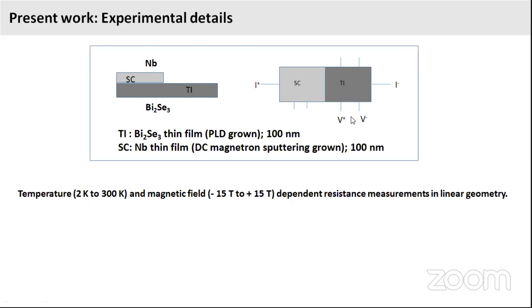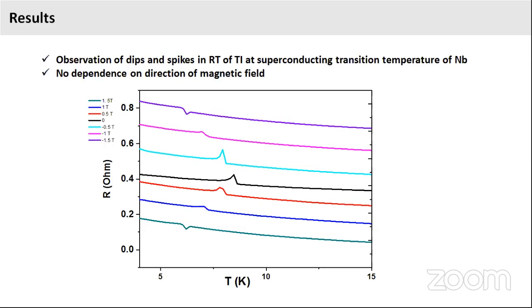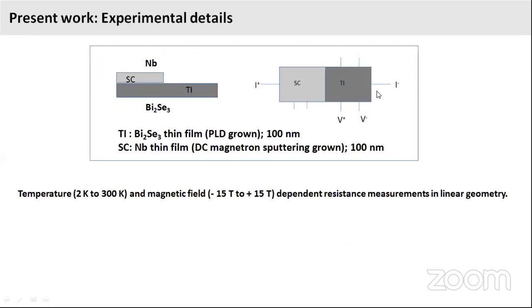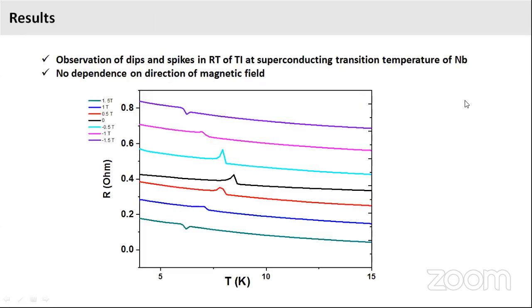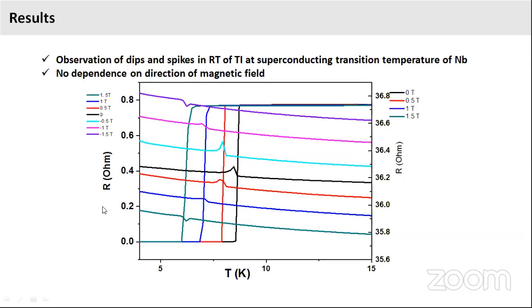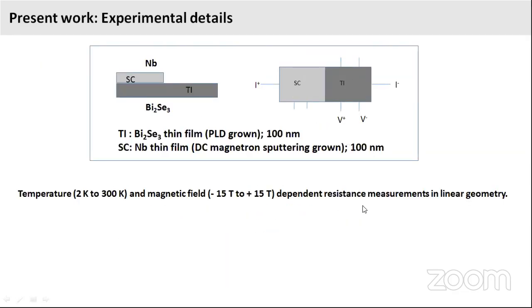Most of what I discuss today will be on what is happening on this uncovered TI. What is the effect of this proximity on this uncovered TI region? Okay, so the very first striking result that we saw was at zero magnetic field, this is the RT measurement on the topological insulator while the current is passing across the entire system. We see that there is a spiking that happens in resistance. And this spiking, interestingly, is occurring at the superconducting transition of the proximity coupled niobium, which is deposited on the left side, if you remember, this niobium.